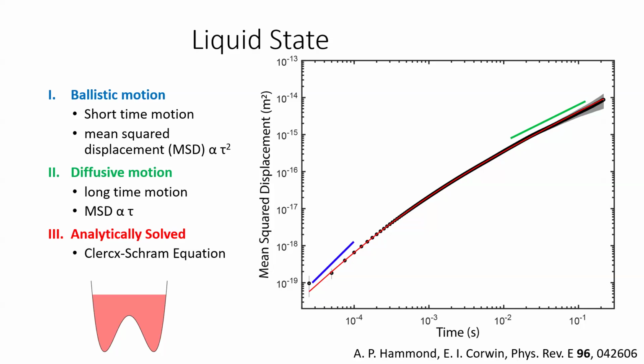So in blue, this is ballistic motion. This has a slope of 2, or a power law of 2. Here is diffusive motion. You'll notice this mean squared displacement goes down to 10 to the minus 19 meters squared. This corresponds to a couple of angstroms. But I had told you that the IID localization noise was 2 nanometers. But because the localization noise is random, it gives you a noise floor that you can subtract away.